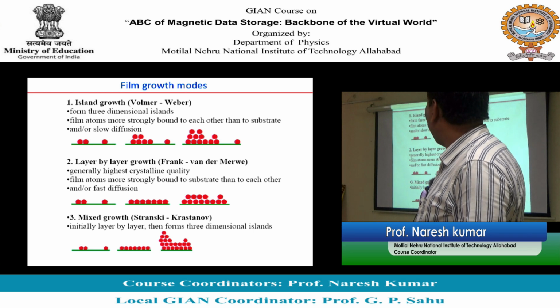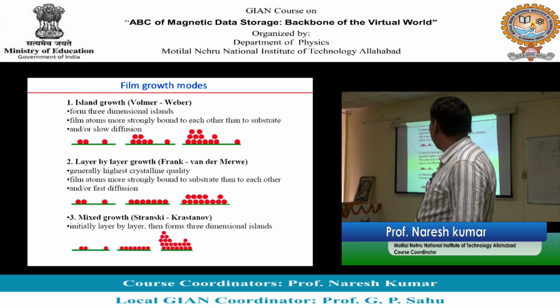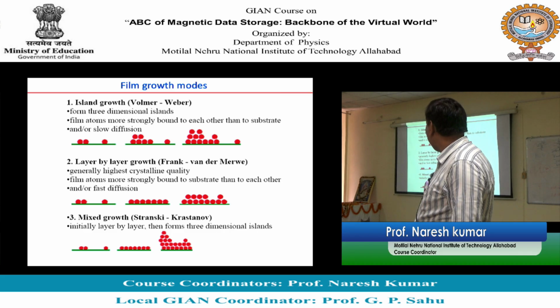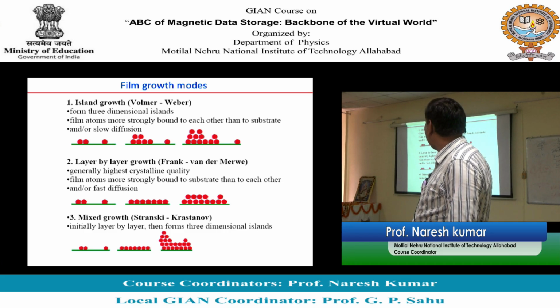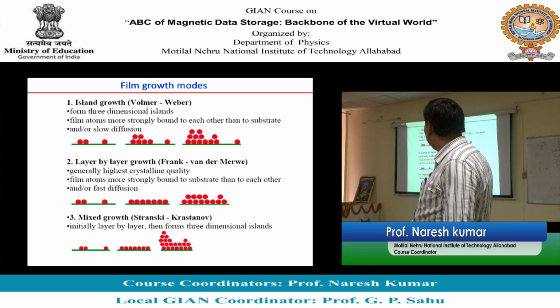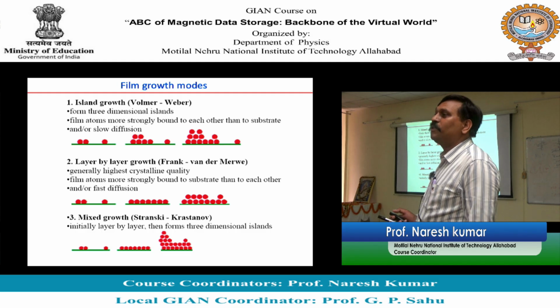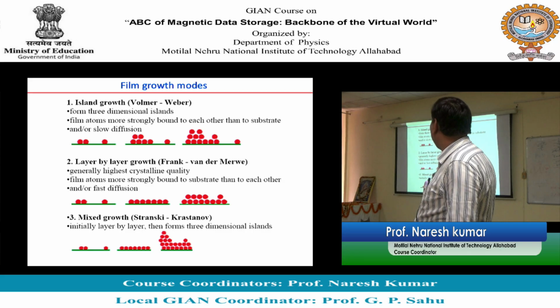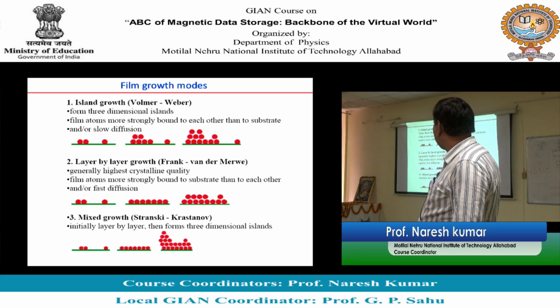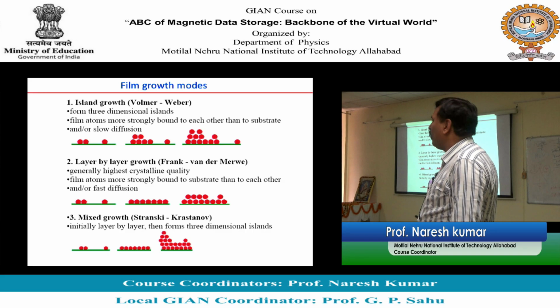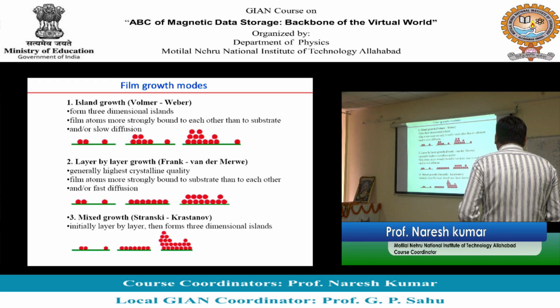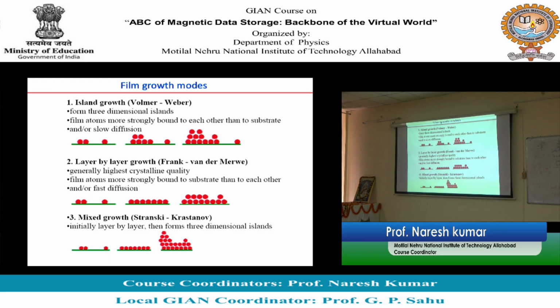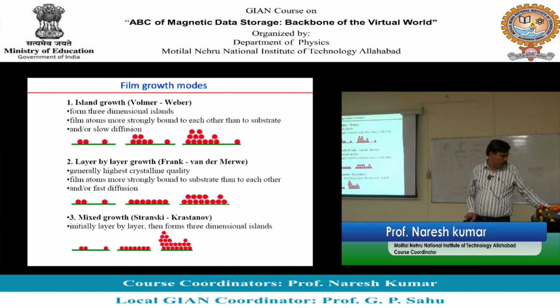And in this island growth, there are interactions between these atoms. So if the interaction between atoms is more as compared to the interaction of atoms with the surface of the substrate, then the growth is island. You have layer by layer growth where the interaction of these atoms with the substrate surface is more. Then you have the first layer and then the next layer. Then there is mixed growth, where initially you have layer by layer, then islands grow. So these are the three well-known thin film growth modes.